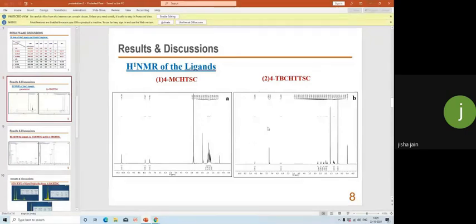In the case of the tertiary butyl cyclohexanone thiosemicarbazone system, the NH peak appears at 8.585 ppm, and the NH2 gives two peaks. The first one is a doublet that occurs at 7.263 and 7.223 ppm, and the second one is a singlet that occurs at 6.168 ppm. And then the tertiary butyl group gives a high intensity, sharp singlet that occurs at 0.886 ppm.